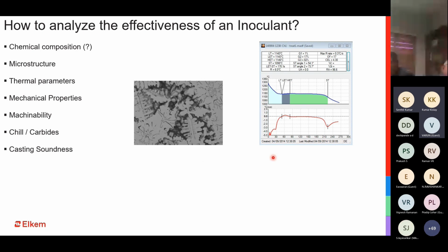But then how do you analyze if your inoculant is good? How do you analyze if your inoculant is working properly? Can you tell by looking at the chemical composition? Yes and no. You will not have an increase of any other element, basically. Maybe silicon, about 60% of your inoculant addition will be silicon. So you'll have some increase in your silicon. But just having an increment in silicon does not ensure that your inoculant is working. That is basically ensuring that your inoculant is added. So if you add the inoculant, you will have some silicon increase, but that is just a partial confirmation that the inoculant has been added.